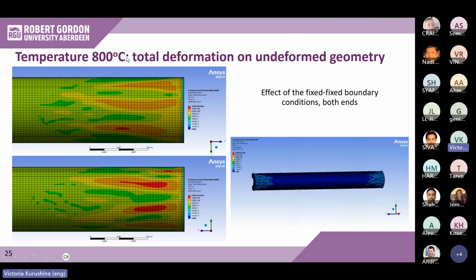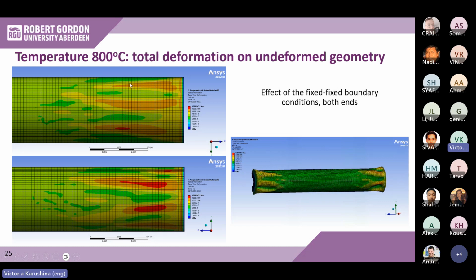Right. So if we project the total deformation result on the undeformed geometry, we will see something similar to these contour plots. We can see clearly the effect of the fixed boundary conditions for the temperature of 800 degrees. The result you see here is for this outer silver layer, which would experience one of the highest thermal expansions. So this is another view of the total deformation. You can see that around one of the ends you would have higher deformation, the areas with the highest deformation being on the top outer silver layer.